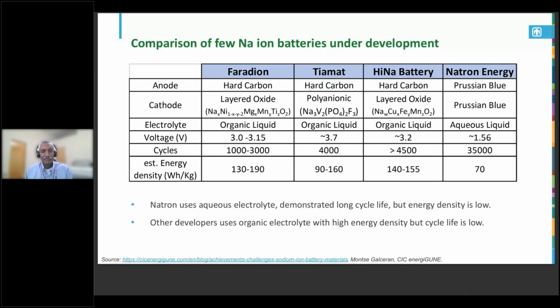Here I try to summarize, based on the literature information, some of the different types of sodium-ion batteries that are currently being developed by Faradion, Tiamat, HiNa, and Natron Energy. Anodes, all the first 3 use hard carbon, except Natron uses Prussian blue. That is the only company using Prussian blue analogs for both anode and cathode. Faradion is using layered oxide, Tiamat is polyanionic. Electrolyte, first 3 are using organic electrolytes. Natron is using aqueous electrolyte. So you can see that voltage is lower compared to the other ones. Because of that, energy density is low.